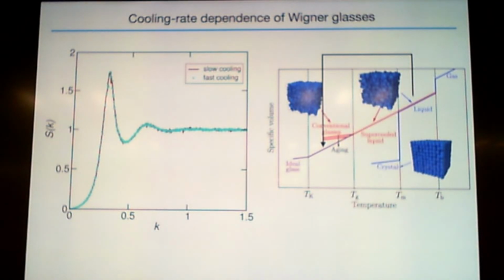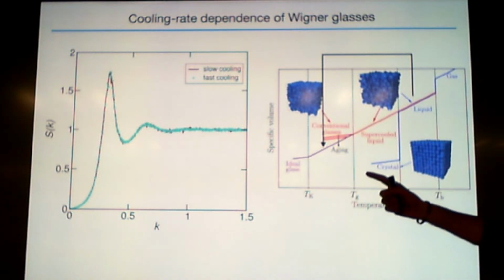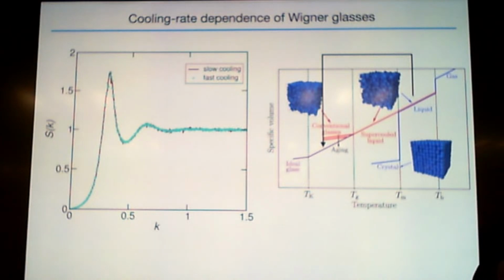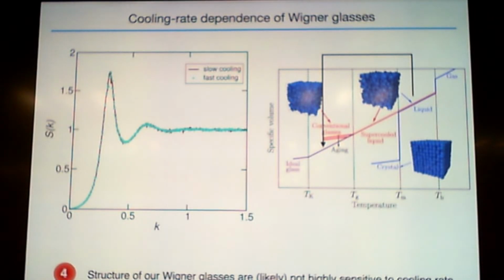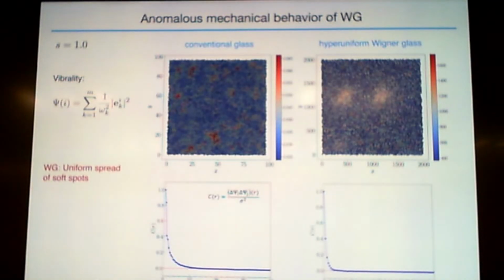And I believe this is not the case in ordinary glasses. If you use different cooling rates, you get different local structures. That also depends on the glass models. But here, the long-range interactions basically cause, we believe, a quick communication between all particles, and the system doesn't care much about the cooling rate. And that's another take-home message. Maybe 2 more minutes.